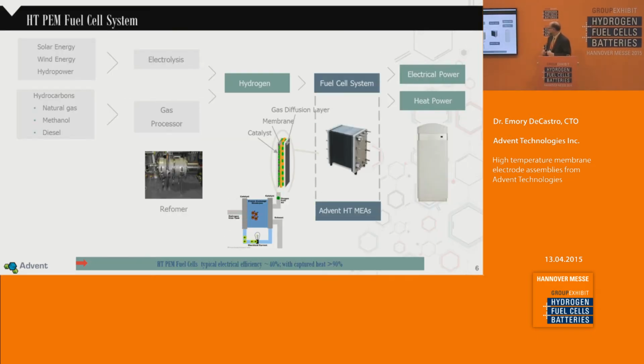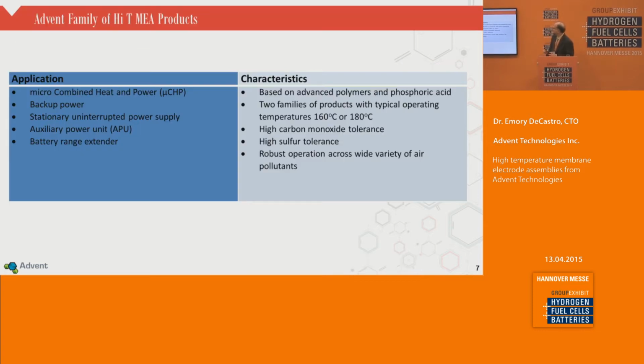Within the Advent business, we specialize in the membrane electrode assemblies. It's our customers that typically make stacks and then incorporate those stacks into the system. So we're really an MEA provider. We actually have two families of high-temperature PEM today. They both share the same characteristics. One, both are based on advanced polymers and phosphoric acid, operating between 160 and 180, which means high carbon monoxide tolerance, between 1 and 3% CO.